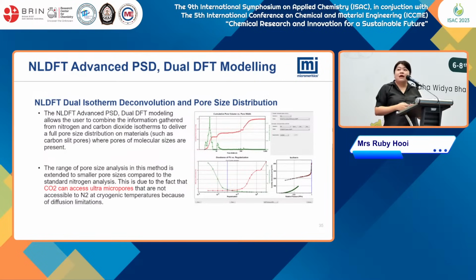So the dual DFT modeling allows the user to combine the information gathered from nitrogen and carbon dioxide isotherms to deliver a full pore size distribution on materials such as carbon slit pores, where pores of molecular size are present. The range of the pore size analysis in this method is extended to smaller pore sizes compared to the standard nitrogen analysis. And in certain samples, we can even go beyond to ultra micropore samples. CO2, with its smaller molecules, is able to access these better compared to nitrogen at cryogenic temperature because of diffusion limitations. So instead of using nitrogen, we can use CO2 for the ultra micropore samples. So you are able to combine two of these isotherms together to further deconvolute and understand the pore size distribution of the samples.